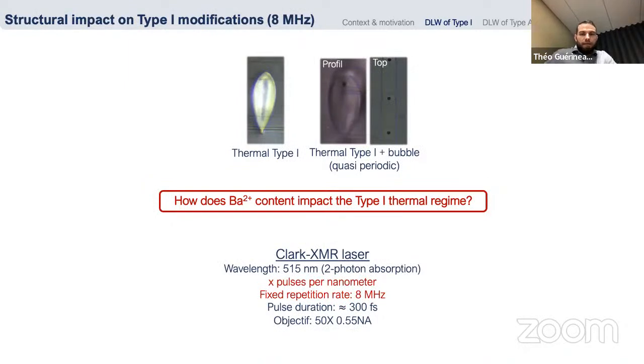But in our case, we want to generate some waveguides. It means that the profile should be as circular as possible. And so we will be more interested in the type 1 thermal regime. So we were wondering how the barium content will impact this type of regime. In this case, we fixed the repetition rate at 8 megahertz, but we left free the number of pulses per nanometer.